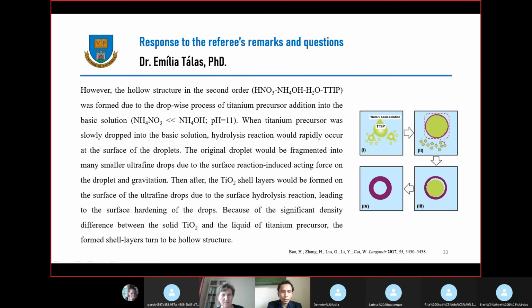However, for the second dosing order, this solution, we mix it firstly, and then the last step was the titanium precursor addition with the dropwise method. So when the titanium precursor was slowly dropped, the solution was a basic solution because the volume of the ammonia was more than the nitric acid. pH should be around 11. So when the titanium precursor was slowly dropped into the basic solution, the hydrolysis reaction would rapidly occur on the surface of the droplet, like in this figure.